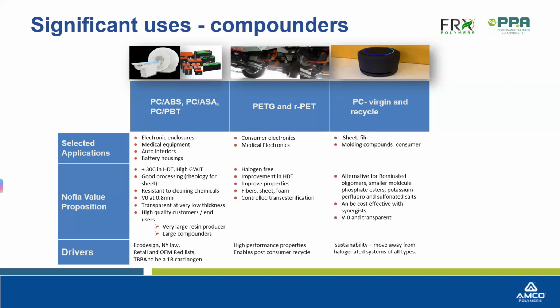PETG and RPET, that's PETG, glycol PET, and recycled PET in consumer applications, housings primarily, but in components as well. And here we can offer a good balance of mechanical properties, and post-consumer recycle levels can be increased. In PC, we work well in virgin and recycle applications. These are largely sheet and film applications, but we have been introduced into molding compounds for consumer electronic applications, and that's a recent initiative, and that also incorporates recycled content. We can maintain transparency, and we can achieve V0 down to as low as 0.8 millimeters.